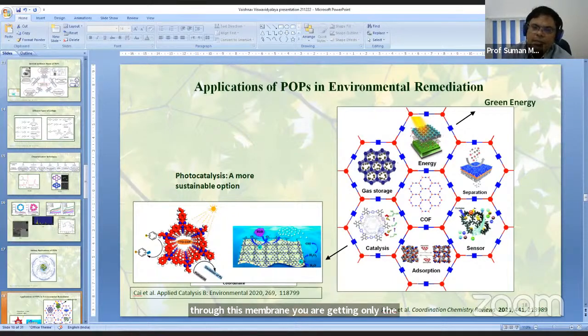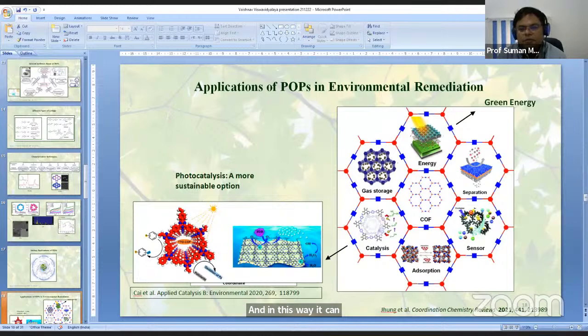It is because the covalent organic framework or covalent organic membrane that has been synthesized has a pore size of something around 1 nanometer in diameter. Now, if you consider the size of the rose Bengal dye, it is bigger than that. But the nitroaromatics have a smaller size of 0.7 nanometer, so they can pass through the pores of this covalent organic framework. In this way, it can help to trap the dye and allow the marker molecule to pass.